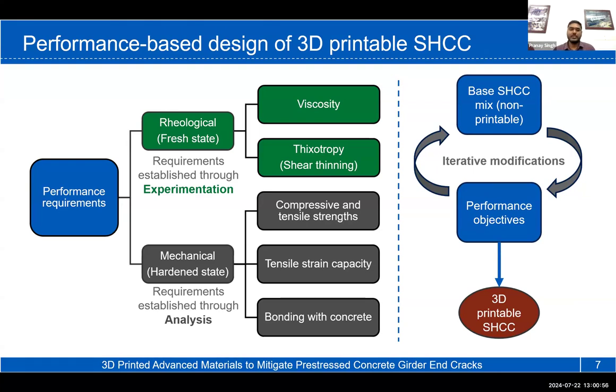And how we are trying to achieve both these objectives is through iterative modification. So we started with a base strain hardening cementitious composite mix that is of course non-printable. It was developed earlier in our lab, and it has that strain hardening behavior. We are modifying its ingredients and changing the proportion of the ingredients in a way that the strain hardening behavior is retained, and it additionally achieves that rheological behavior to make it possible to 3D print.